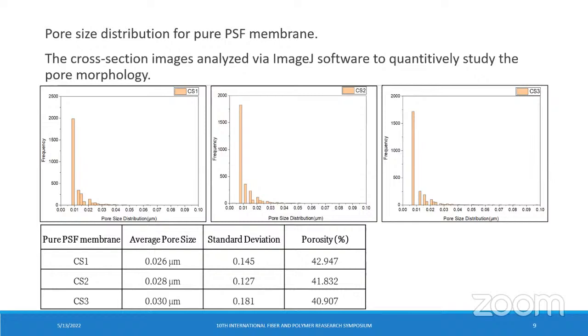In the table, you can see the average pore size measured for each cross section, and we can see that they are all within acceptable standard deviation. The average porosity is calculated for these 3 cross section images, and we found that the average porosity is 42% for the pure polysulfone.